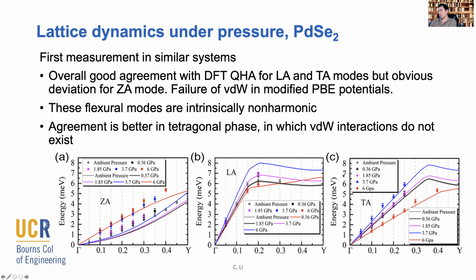And there are some small disagreements between the calculation and the measurement, but I would attribute many of them to either the potential itself, or there could be a different lattice parameter predicted by DFT versus what you would expect under the pressure in the real system. But they are actually pretty good in terms of first principles simulation. There is a significant difference between the two phases, but that's also expected because we have a phase transformation, and now the phonons behave quite differently once we reach 6 GPa. But the main interesting result is shown in panel A, which shows this ZA mode, a flexural mode I was referring to.